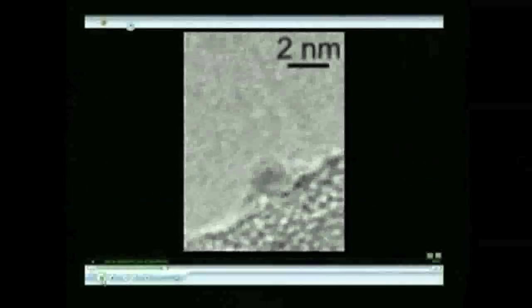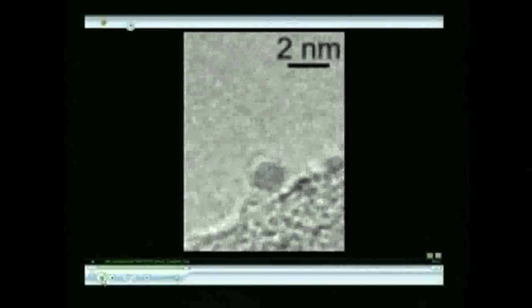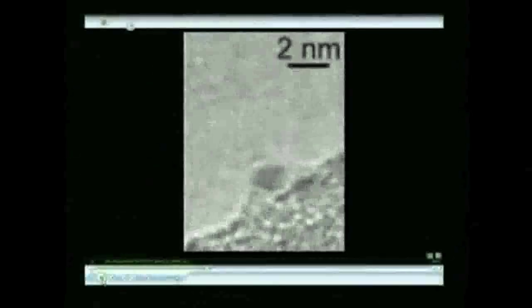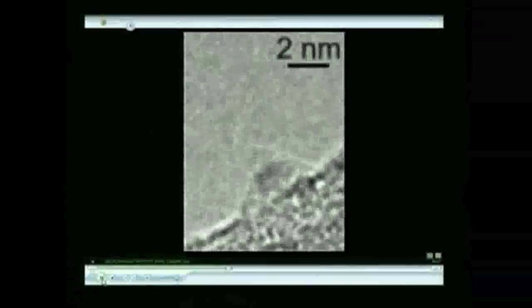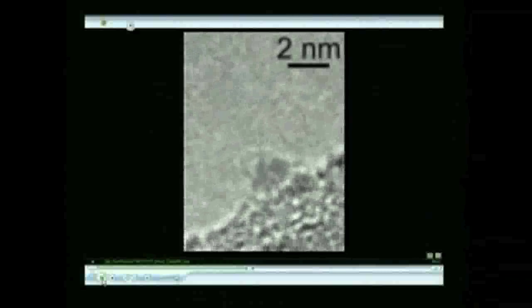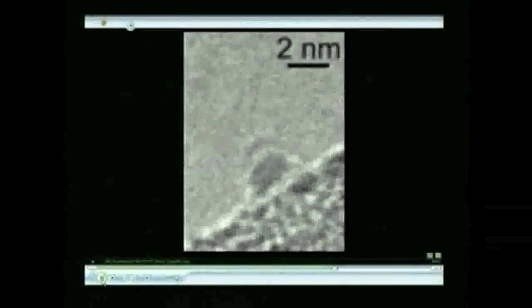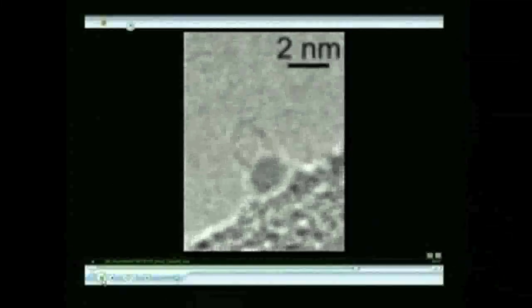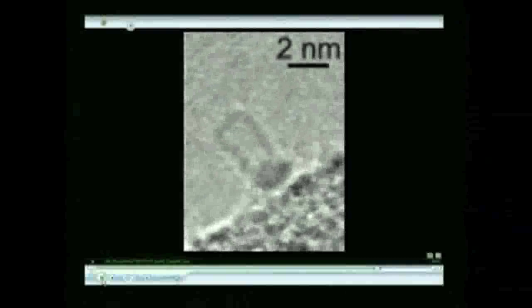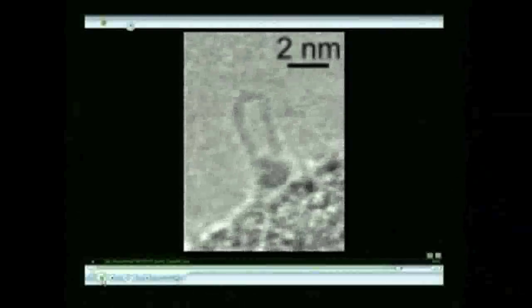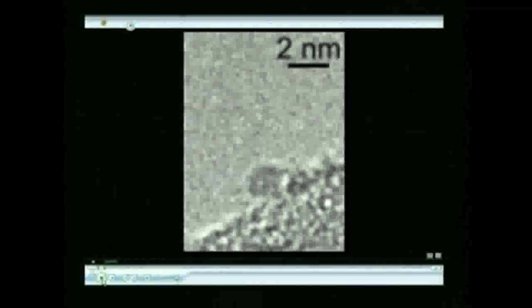The movie is quite good quality for present standards. What you observe is a carbon cap starting to form and disappearing, or maybe being hidden behind. A new one appears now, but there's always a cap starting to cover the particle, and then it starts to be a bit longer. It covers partly the particle. You get the cap a bit longer. It seems to be stable, and now it's starting to be amplified. It gets longer and longer, and at the end we have a small nanotube. Okay?